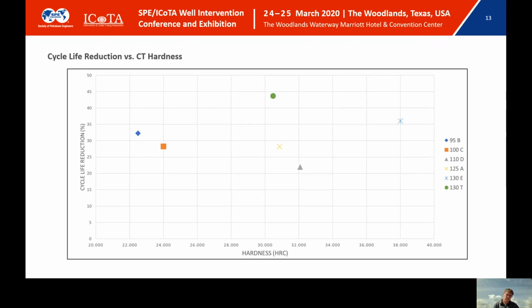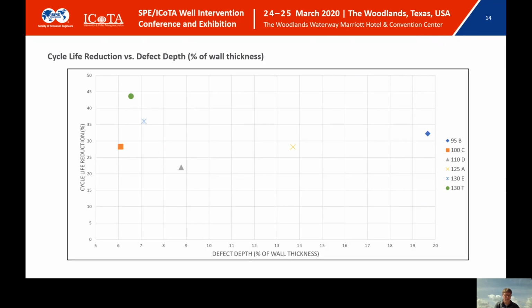This slide talks about the cycle life reduction versus coil tubing hardness, because we thought there might have been a trend there. And again, it's pretty difficult to draw any conclusions from this data. The one thing that you'll see recurring over the next few slides is that the cycle life reduction, on average between the two samples for each specimen, is between 20 and 45%. And I think that's what to expect. But there wasn't a great correlation between cycle life reduction and hardness.